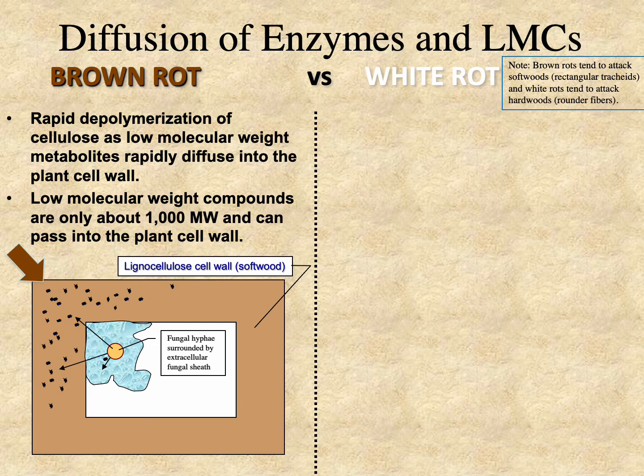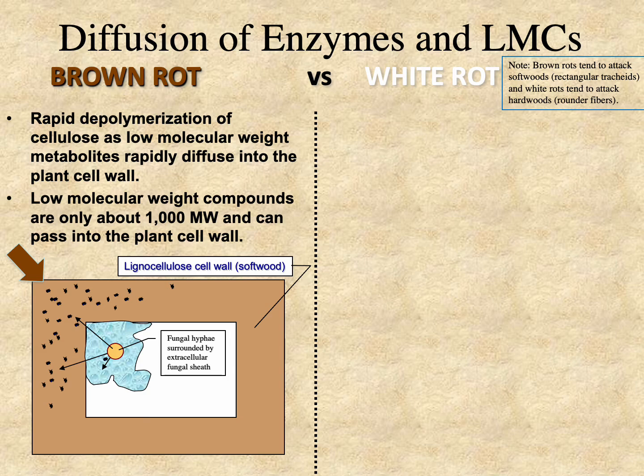This is all done by hydroxyl radicals generated through the chelator-mediated Fenton system. The way hydroxyl radicals attack lignin is they depolymerize lignin, and then they immediately re-polymerize it. You can actually see this with atomic force microscopy — the lignin starts to form little nodules as it clumps together. This is the brown rotted lignin that persists in the forest for hundreds of years, and some reports suggest even over a thousand years in this re-polymerized form.